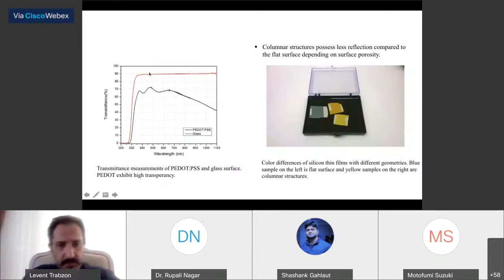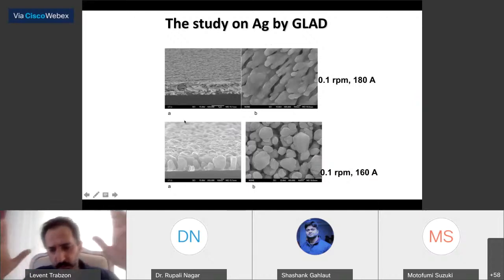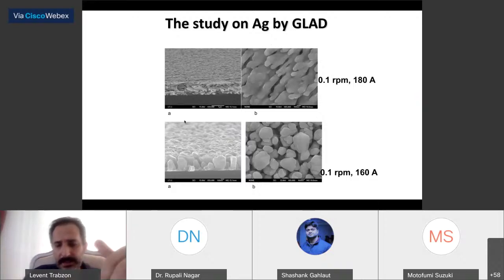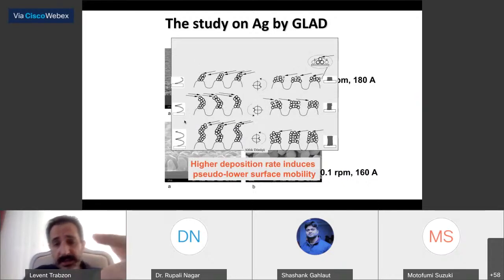Transmission is not bad with respect to the glass. Anyway, I'm just giving two more slides. We also studied, it's unpublished data, silver by GLAD, which is not an easy material, as you already know, because the melting temperature is not so high. But you can notice that a higher deposition rate induces pseudo lower surface mobility. This is one observation we have seen.